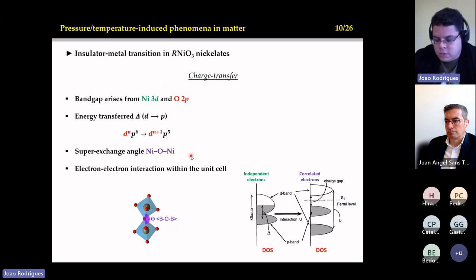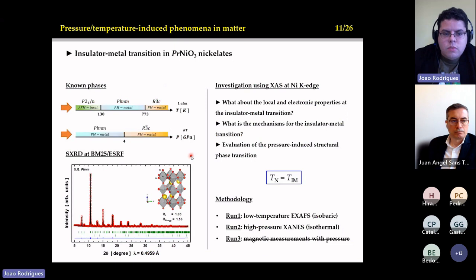So it is a nice playground to understand basic concepts in physics, mainly the relation between the spin and the lattice, but also for applications, as I mentioned, for spintronics. So the case we studied in this investigation used the praseodymium phase, for which there is this phase diagram. Basically, you can induce 3 different phases under temperature and 2 phases under pressure. Okay, we have the insulator-metal transition to the metal, and from the monoclinic phase to the orthorhombic phase at 130 Kelvin. And then if you heat up this sample, you have the rhombohedral phase, which is very symmetric, but also metallic, like the orthorhombic one. And under pressure, you can also induce the same transition.